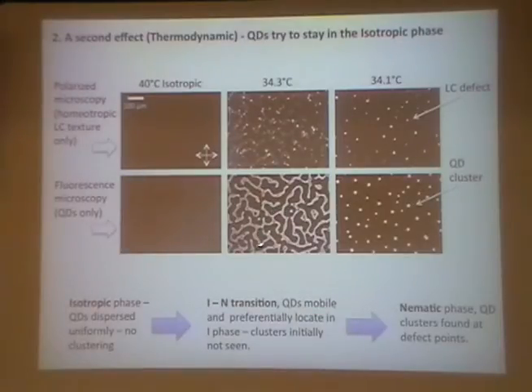What's happening is the spatial position of the quantum dots is very dynamic. They pretty much all move to the remainders of the isotropic phase. They don't want to be in the nematic phase as it comes in. And because the system has enough thermal energy, and they're very small, they're just able to move into the isotropic domains. So you can see they are mostly there. All this white here is quantum dots, and it matches really well with the remaining isotropic domains. Eventually, those domains close up, and as they close up, they collect the quantum dots into a spot, the last place where the isotropic was. That's where the quantum dots end up. So I think when you're making a material, this is even more significant than the clustering effect, that they just want to phase separate out. And so we can see here, where the defects end up, that's where the quantum dot clusters end up as well.